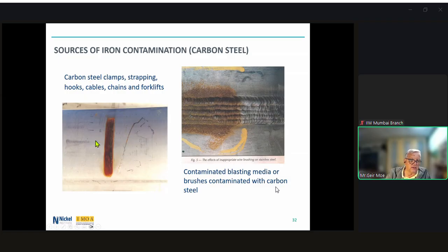And here we can see contamination from a carbon steel strap that was used to, say, bundle up this stainless steel, but there was no insulator, say, like plastic or wood or paper, between the carbon steel strap and the stainless steel surface. And in here we've got contamination by blasting media, or it could even have been a brush that had been contaminated with carbon steel particles and was brushed onto the stainless steel.